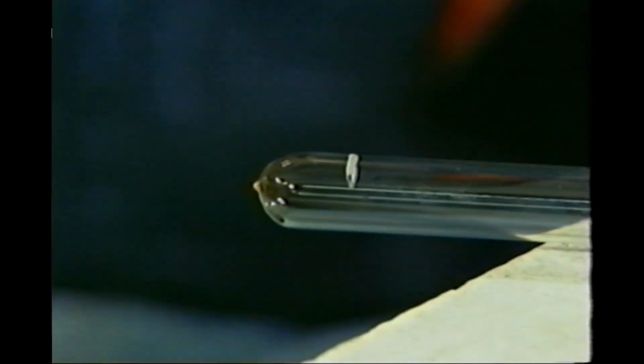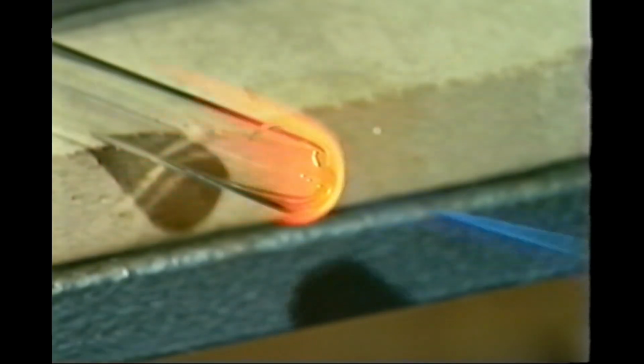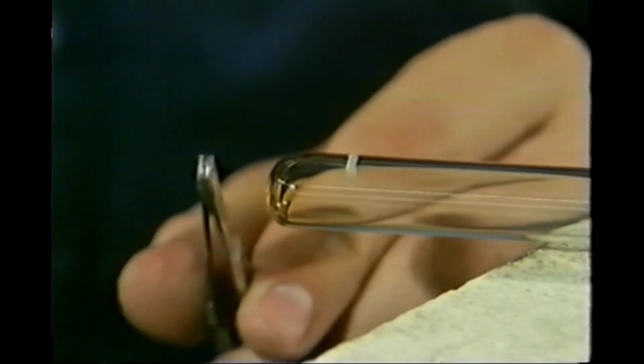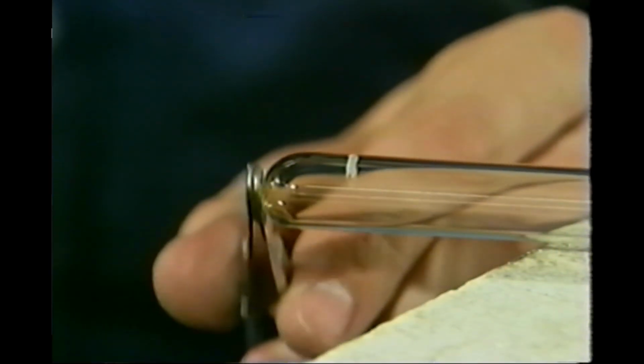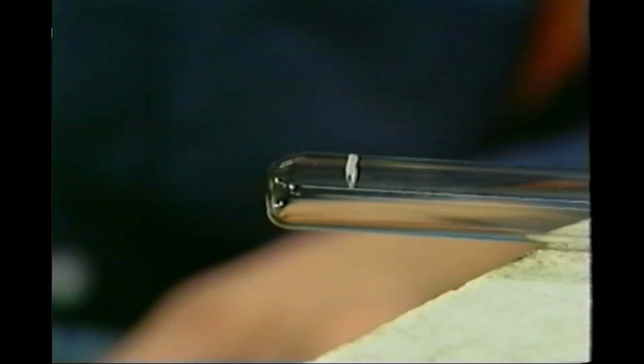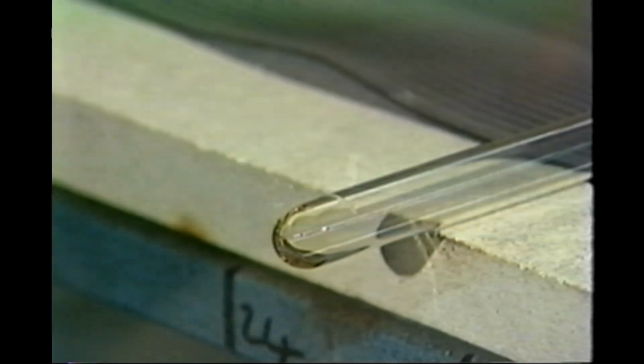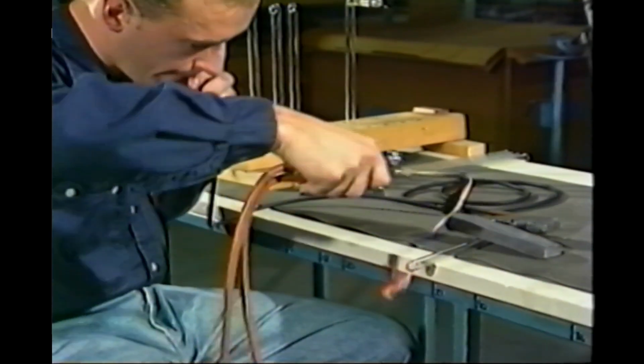To shape the butt end again, point the flame directly at the closed end, allowing the glass to melt back slightly. Remove the flame and blow the glass out until it flattens at the end against the flat surface of the tweezers, forming a neat, semi-rounded closed end to the tube with the correct wall thickness. Anneal thoroughly.